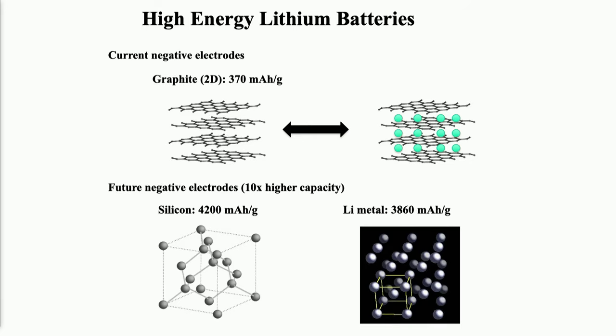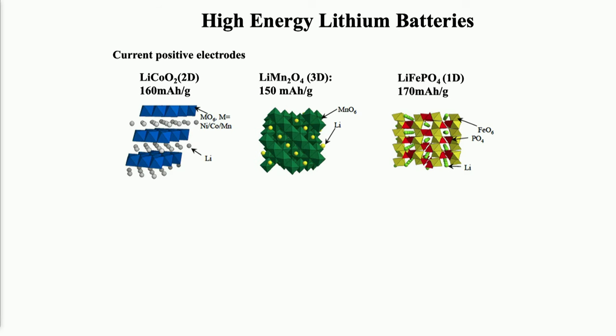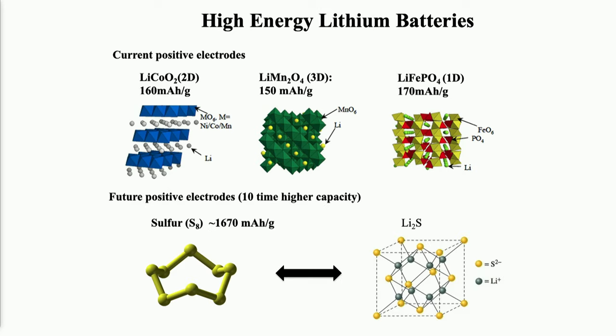Why don't we use the new materials? If you can store a lot more charge, like with lithium, you increase the amount of energy you store tremendously. On the cathode side, it's similar. The top three cathodes are the basic structures for lithium-ion batteries: lithium cobalt oxide, lithium manganese oxide, and lithium iron phosphate. They store close to 200 milliamp-hours per gram, but we have something that can store a lot more: sulfur. The cost is also very low with sulfur. This gives you 1,700 milliamp-hours per gram. So this is the question we ask.